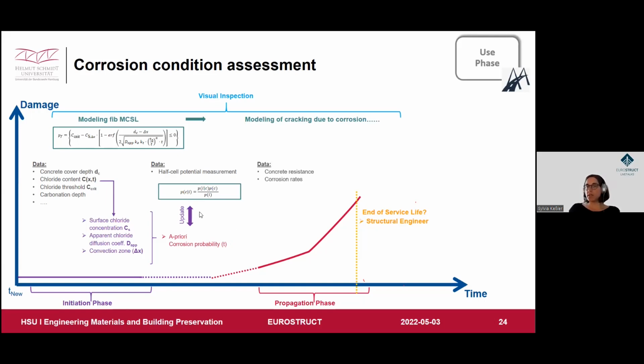As soon as we know there's corrosion going on, a very important parameter is the corrosion rate or the concrete resistance, which also gives us a clue on the corrosion rate. The corrosion rate can easily be transferred to the loss of cross-section or the loss of mass due to corrosion. And this is also a very important input parameter for the modeling of concrete cracking.